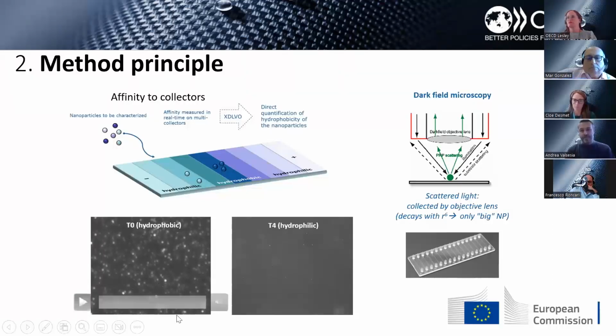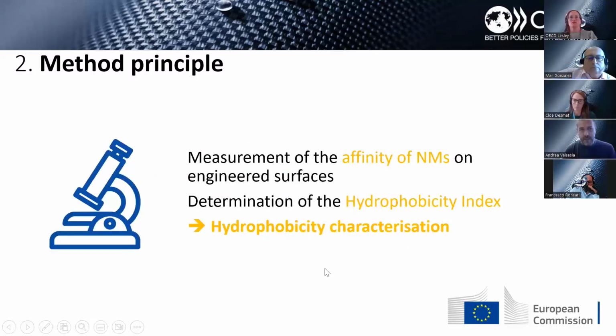So the method principle is that we measure the affinity to engineered surfaces, and by using the ratio between the three different affinities on the three different collectors shown previously, we are able to calculate a value, a number, which is the hydrophobicity index. This enables us to characterize and quantify the hydrophobicity of the nanomaterials.